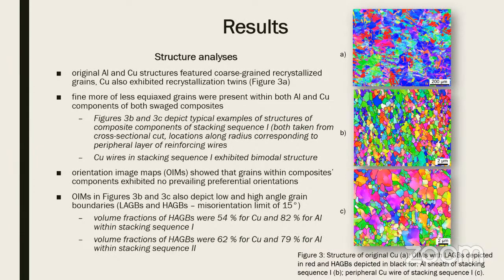In these figures we also see high angle and low angle grain boundaries, and the high angle grain boundaries were prevailing in both the structures. As we can see here, we had more than 50% of high angle grain boundaries in all the components that we looked at, both copper and aluminum in both the stacking sequences.